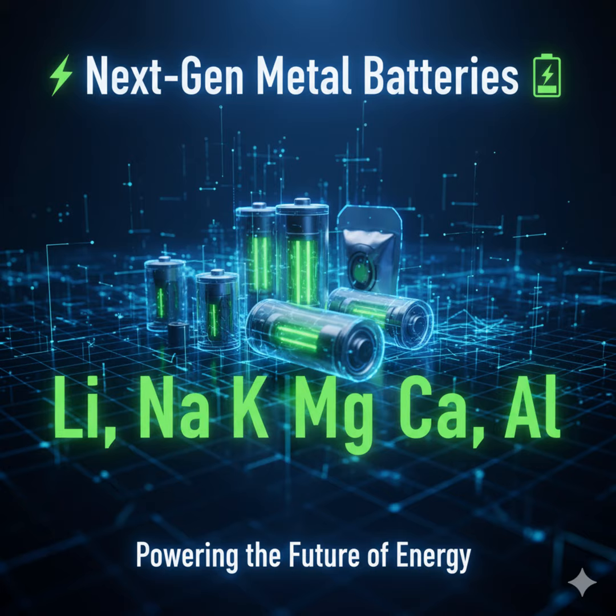But the bad news? The bad news is it's mechanically weak. Remember, the metal anode expands and contracts a lot during charging and discharging. This flimsy organic SEI just cracks and breaks apart under that stress. And when it cracks? It exposes fresh reactive metal underneath. That fresh metal immediately reacts with more electrolyte, forming new SEI, consuming active lithium and electrolyte. It's a vicious cycle. The SEI is constantly being destroyed and reformed, which drains the battery's life over time. It's what the authors kind of call the organic mess.